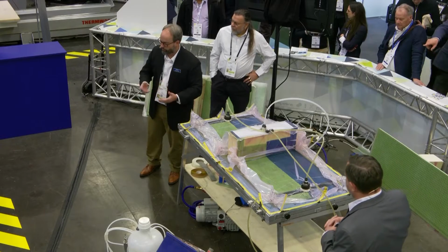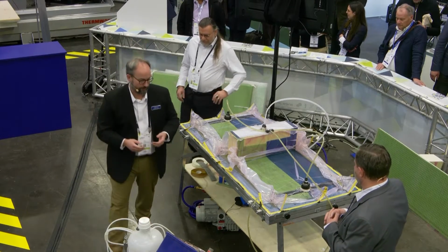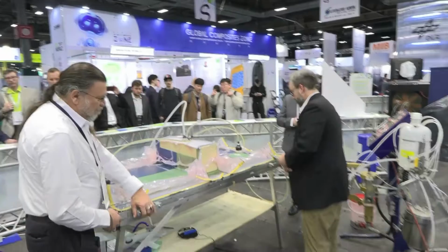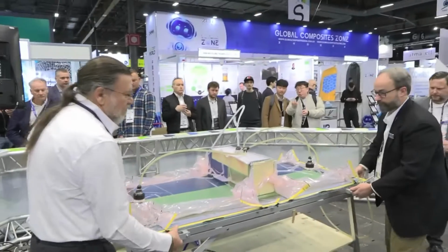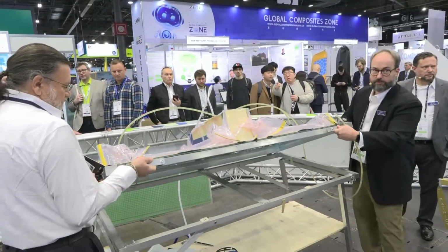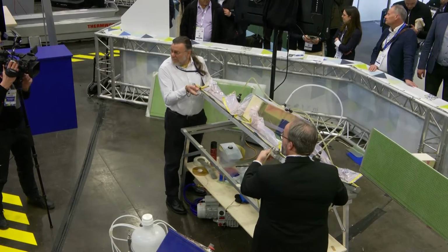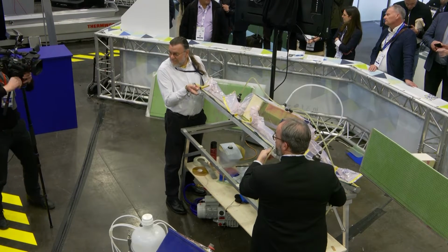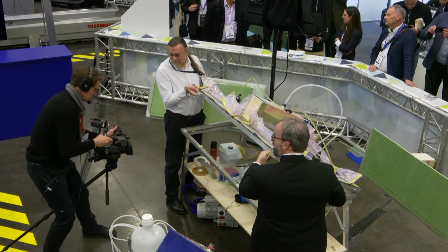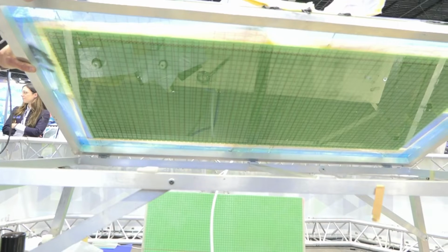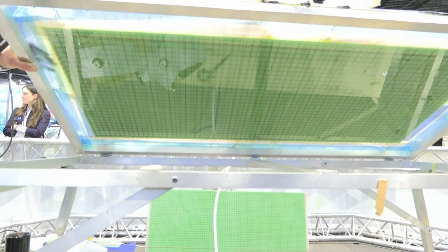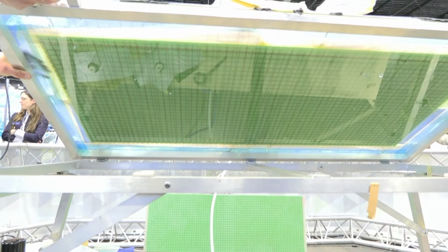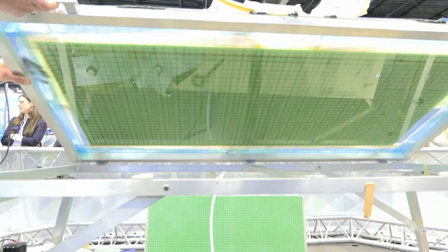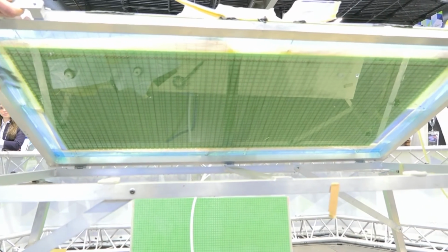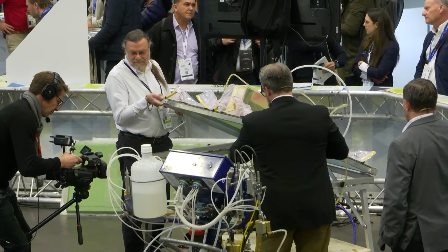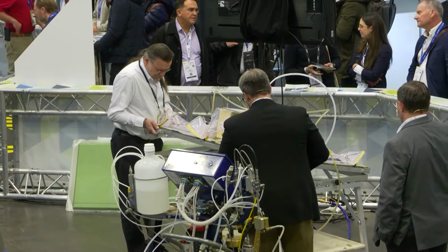So we can show you the underside of the mold again. So you can see that everything's completely saturated. So the glass becomes transparent and the peel ply, so we can actually see the core material through the fiberglass. So the infusion process is very good.